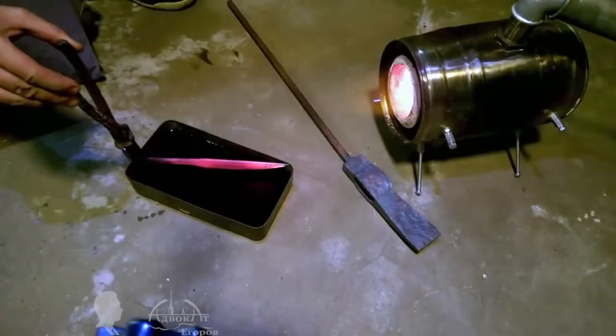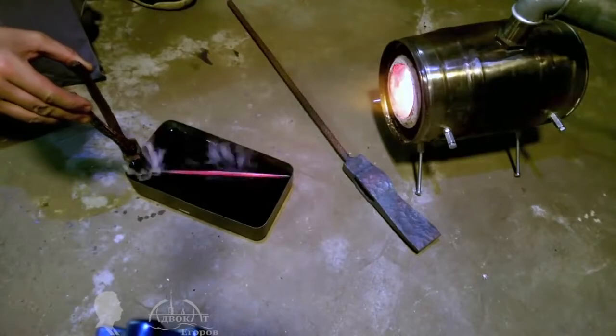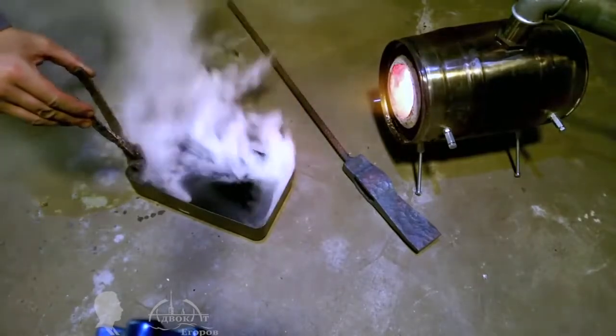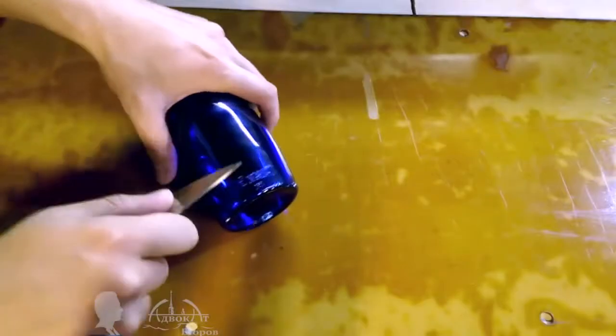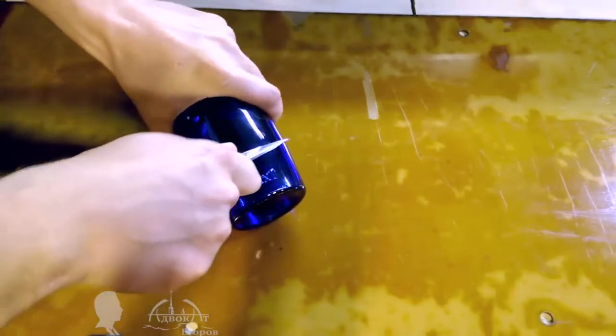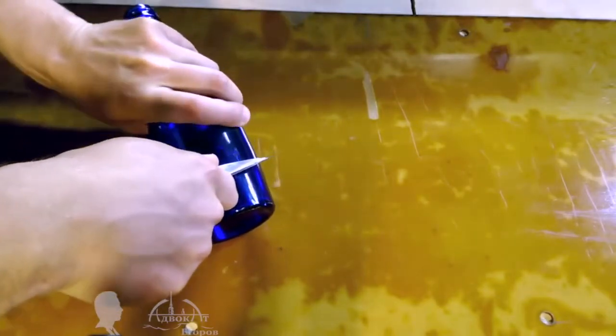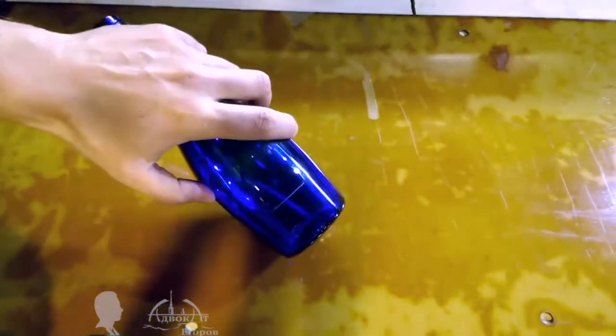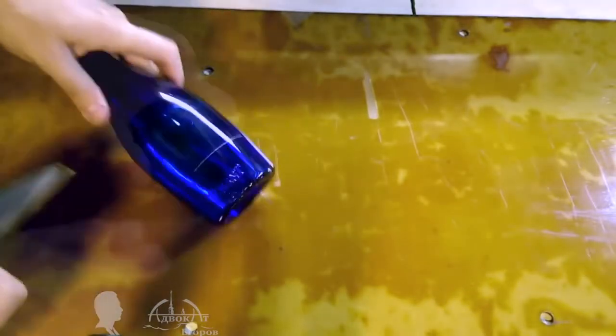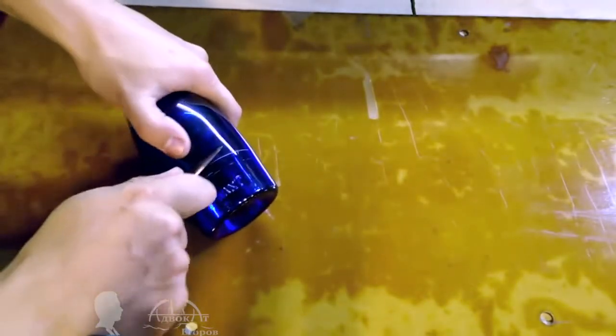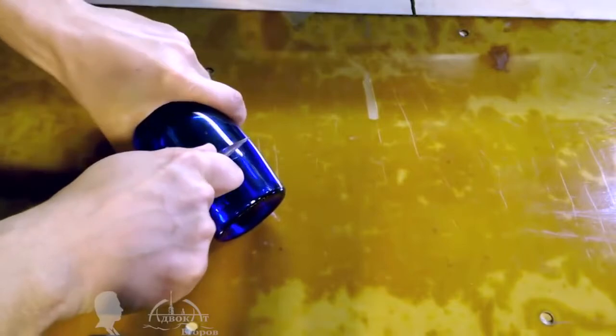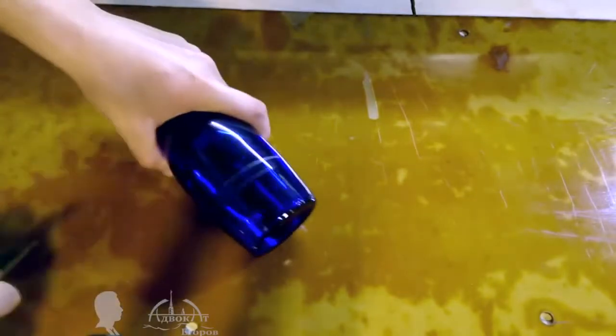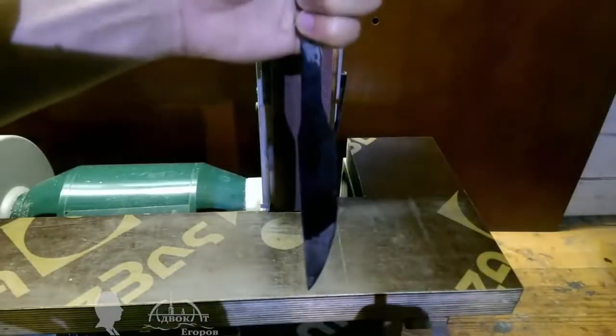Note: for selective tempering, I slowly submerged the blade's cutting edge into oil to give it more hardness. This way, the knife's cutting edge becomes harder and will keep its sharpness longer, while the blade's spine stays softer and fairly flexible. The blade can easily score this bottle because its cutting edge is in the high 50s of the Rockwell range.